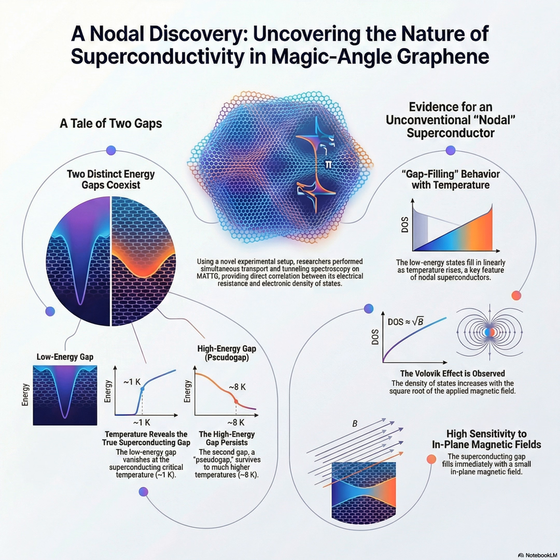Not something they just came up with. Exactly. And they found that the zero bias conductance exhibited a square root dependence on B-perp. It increased proportional to the square root of the magnetic field strength. A square root dependence. That sounds incredibly specific. Why is that mathematical relationship the smoking gun that proves the pairing is nodal?